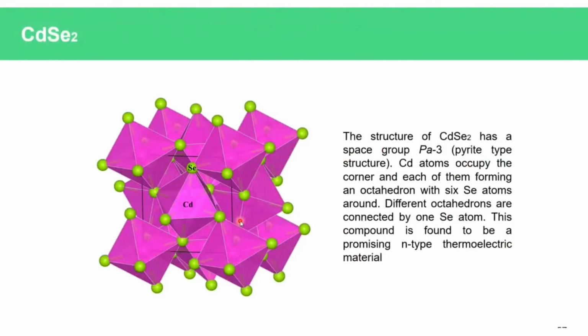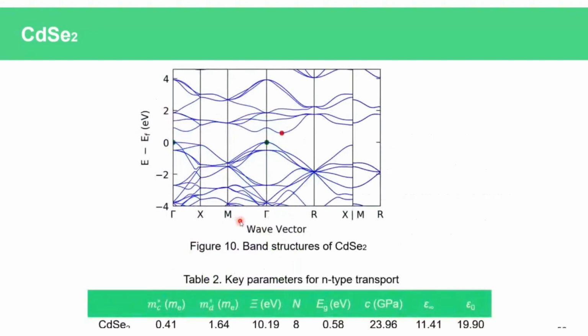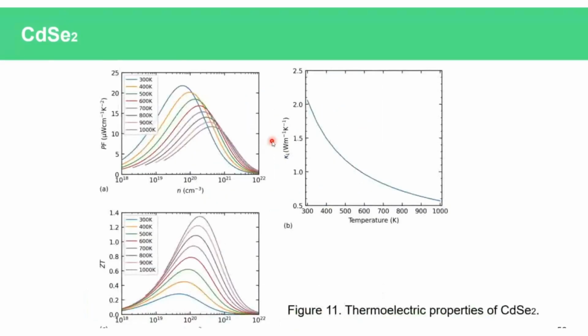Cadmium selenide 2 is one of the good N-type thermoelectric materials we found. It's also a cubic structure with space group Pa-3, and it also belongs to the pyrite type structures. This is its band structure. The VBM is at the gamma point, while CBM is along the gamma-R path. The CBM is dispersive and has small conductivity effective mass. Meanwhile, the band degeneracy of CBM is large, equal to 8, so it also has a large MD divided by MC value.